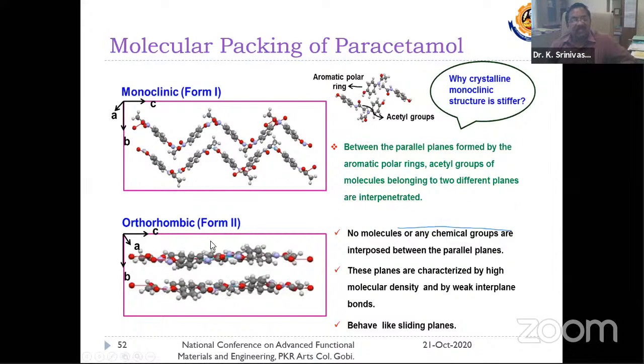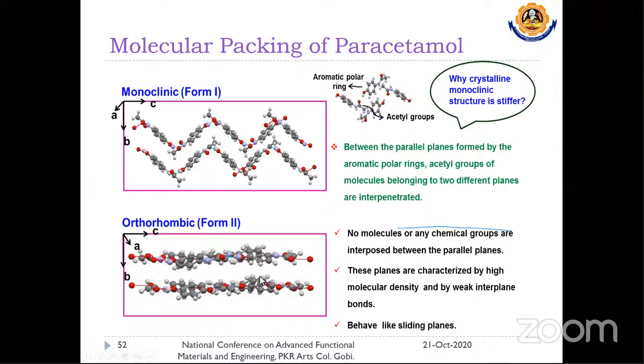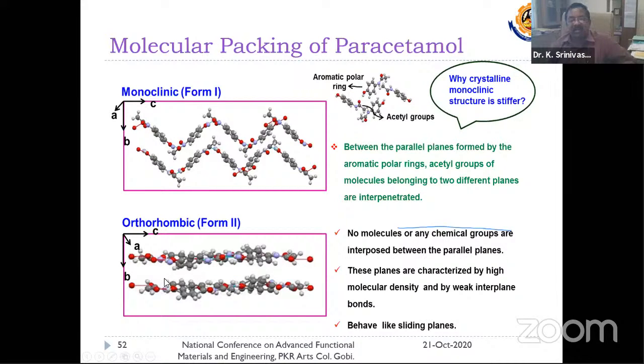Whereas in the other case, the metastable form, it is something like this, with parallel planes. There are no molecules or any chemical groups interposed between these parallel planes. And these planes are also characterized by high molecular density when compared to this one. So you can easily pack these molecules into a smaller volume, and also pack more molecules into a smaller molecular volume. So the tablet size will be very small, very easy to consume, and the efficiency will also be more. In several ways, this form is very much needed by the industry.